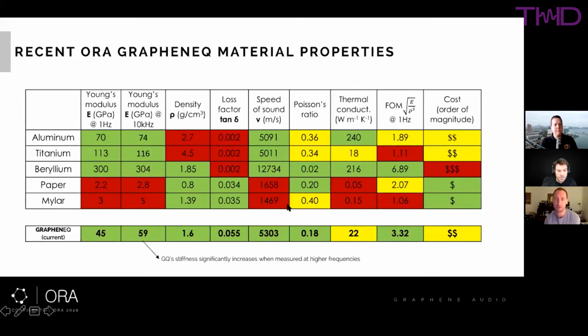And the important aspects here are the Young's modulus, which is a measure of the stiffness of the material, the density, which is essentially how much it weighs for how much you have, and the loss factor, a damping factor, which describes how quickly the energy will be absorbed by the material. So aluminum, for example, has very poor damping, and oftentimes people refer to aluminum tweeters as sounding zingy, and that's largely because they retain energy for a long time and it rings out, giving it that zingy sonic signature. So damping can be very important in achieving a nice smooth frequency response.